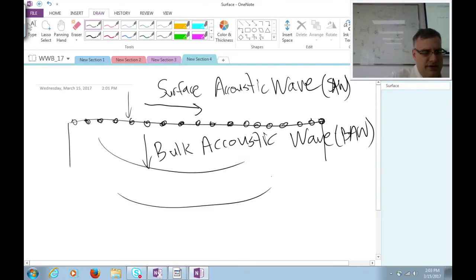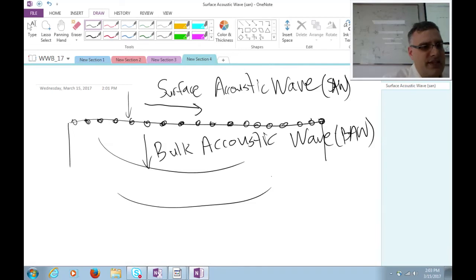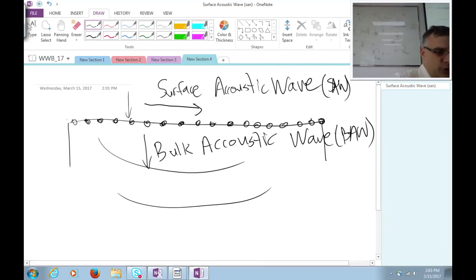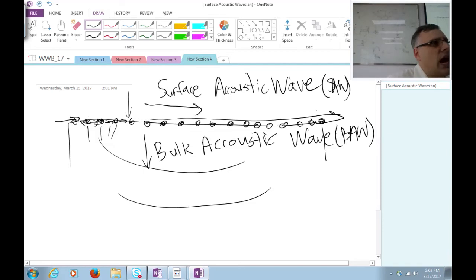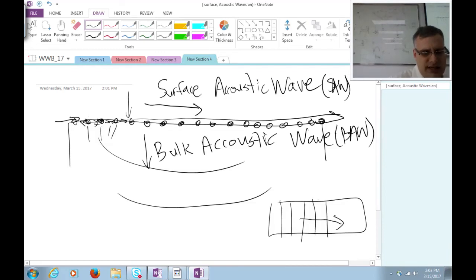The bulk acoustic wave, of course, you bang this on top and then you launch a wave where the mechanical displacement of the atoms in the material travels down and can reflect off of interfaces and the like. The surface acoustic wave is a slightly different wave. This is where you create a vibration and launch it from the side, and these atoms vibrate back and forth and cause their neighbor to vibrate back and forth, and cause this neighbor to vibrate back and forth. But by and large, this wave travels just upon the surface. It stays relatively collimated, which means if I look at this from above and I launch a wave from the end, it travels at uniform velocity, and it doesn't bend or disperse very easily through the material.